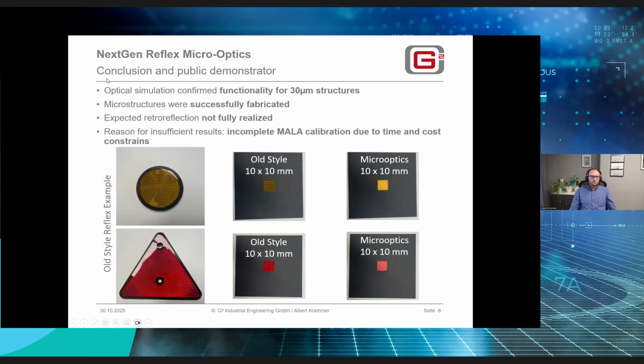Yeah, a conclusion to these steps. We did the optical simulation and confirmed the functionality, basically for these 30 micron structures for this function. The microstructures were successfully fabricated, but the expected measurement results were not realized.